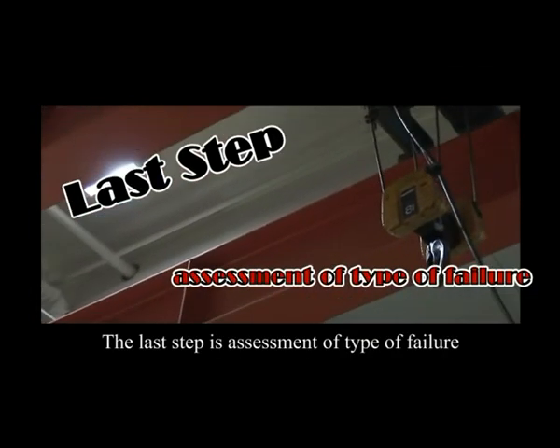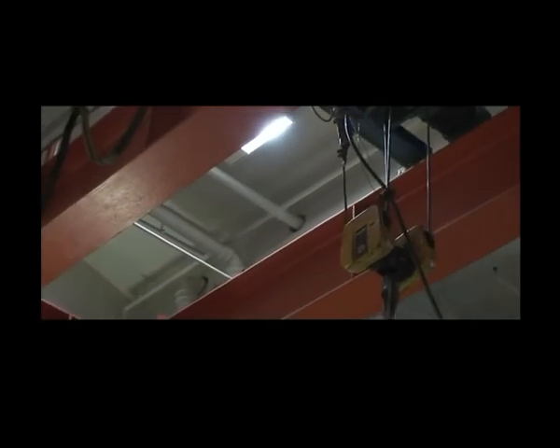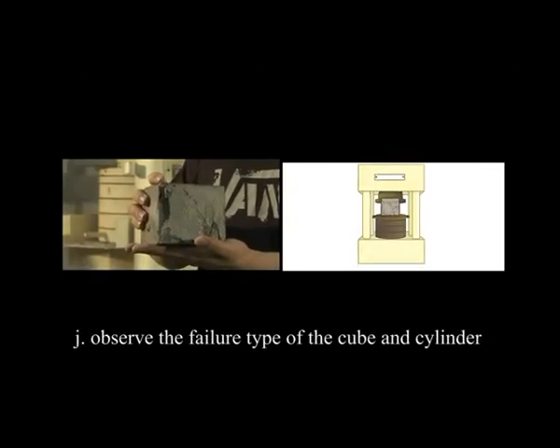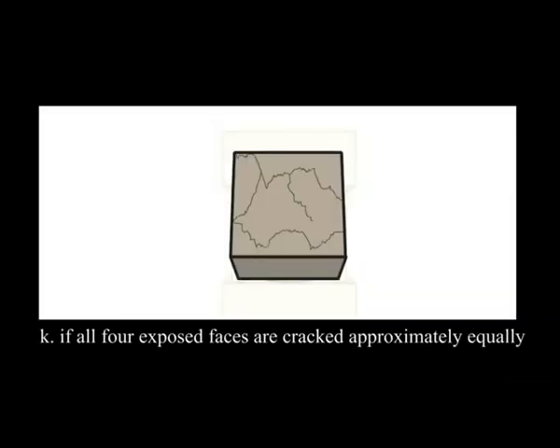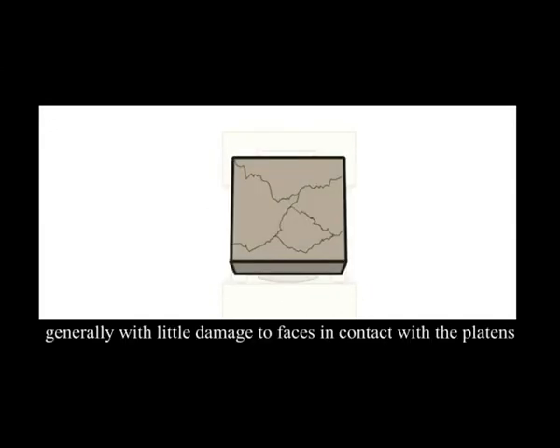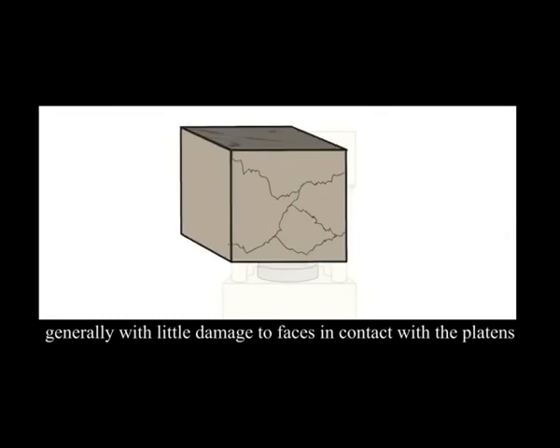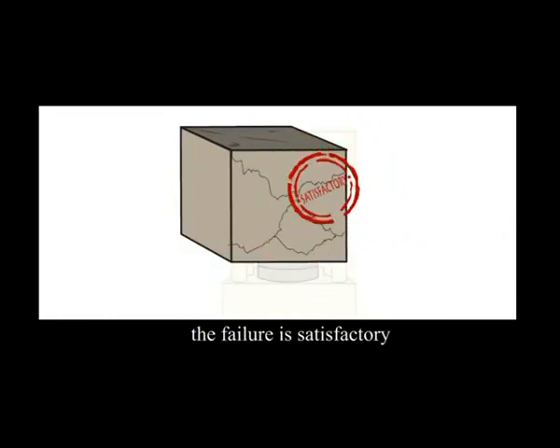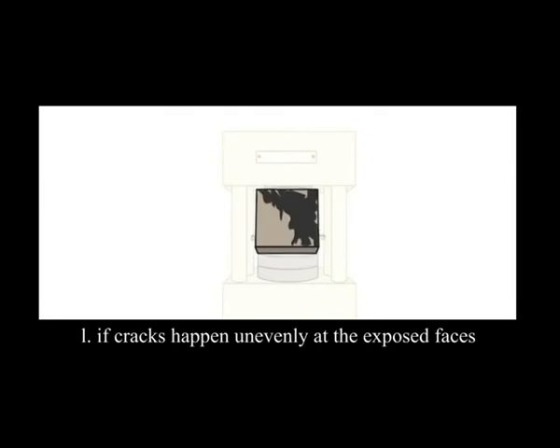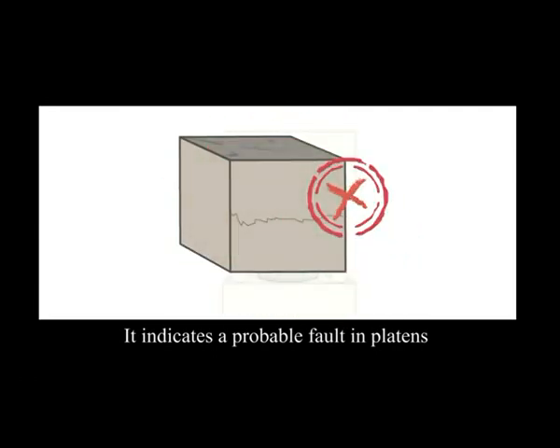3. The last step is assessment of type of failure. J. Observe the failure type of the cube and cylinder. K. If all 4 exposed faces are cracked approximately equally, generally with little damage to faces in contact with the platens, the failure is satisfactory. L. If cracks happen unevenly at the exposed faces, the failure is not satisfactory. Record the failure mode. It indicates a probable fault in platens or in the testing machine.